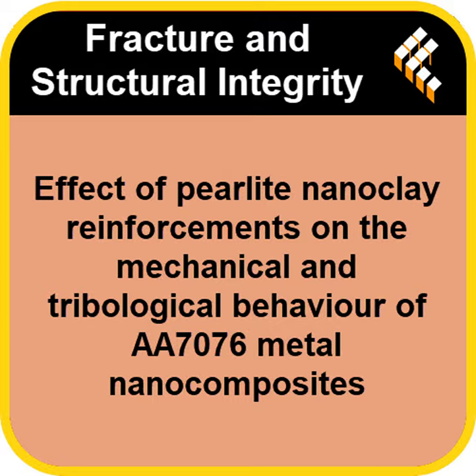Minimal. That was the key finding. Minimal agglomeration, minimal porosity, which really confirms that this specific customized stir casting setup was highly effective for this particular combination of materials. Okay. And the EDS analysis, that just backed it all up. It mapped out where the elements were, showing uniform aluminum and zinc from the alloy, and confirming the bits from the nanoclay were integrated right in there. The structure looks sound. Excellent.